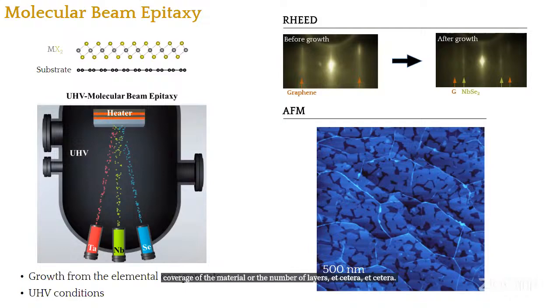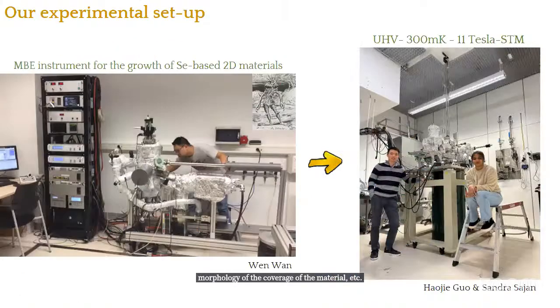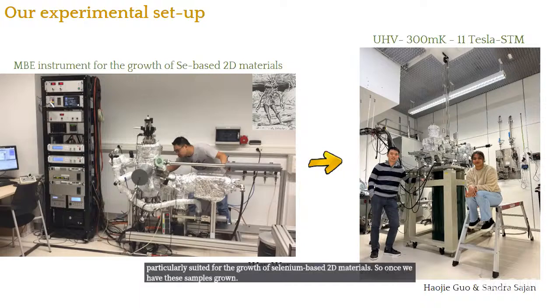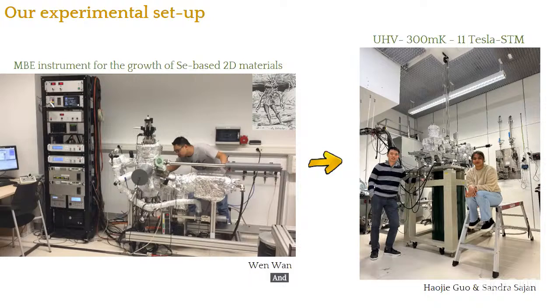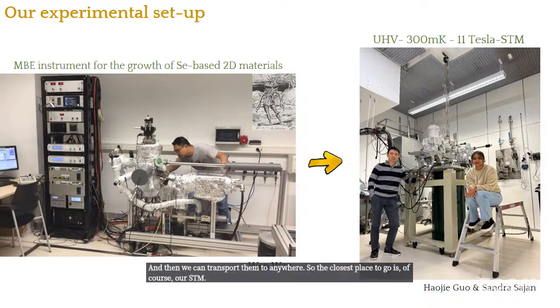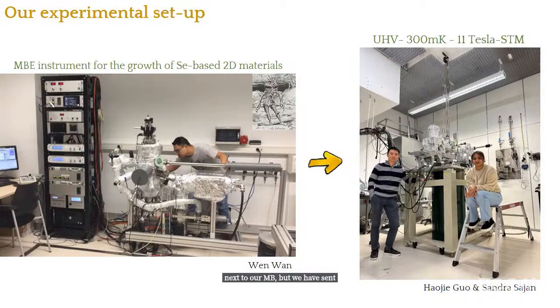Once the growth is done, you can check the morphology and coverage of the material with AFM, or STM, of course. Here I show you a picture of our MBE instrument, which is a homemade instrument, particularly suited for the growth of selenium-based 2D materials. Once we have these samples grown, we cap them with an amorphous layer of selenium, and then we can transport them anywhere. The closest place to go is, of course, our STM next to our MBE, but we have sent these samples to Denmark, the US, etc. And they survive. You just anneal them, you expose the crystalline material, and then you can work with them.